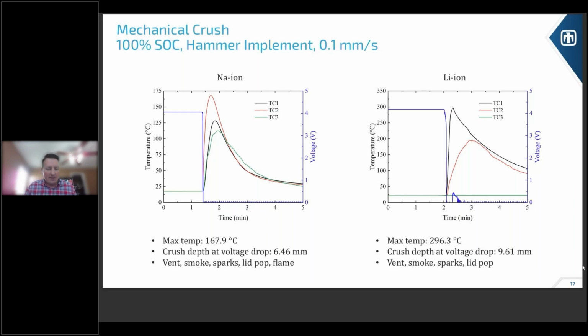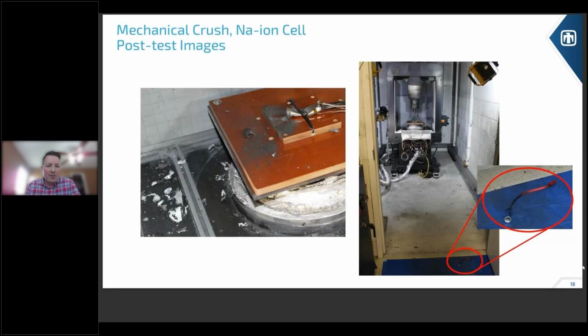So the aftermath of this one, you can see that some of the contents did come out of the cell, so they're not all inside of the cell. But again, it didn't explode, just the lid came off violently. I like to show this, the bottom or the right side image. You see the red circles on kind of the bottom right. There's normally a door closed during this test, and that door was closed. But when we came in, we found the cap of the 18650 had actually ejected all the way out of the bay underneath that door. Next.